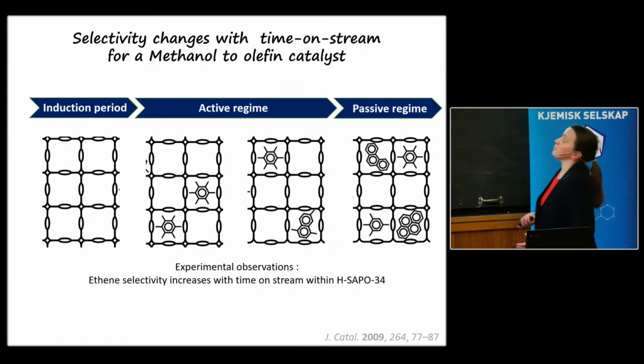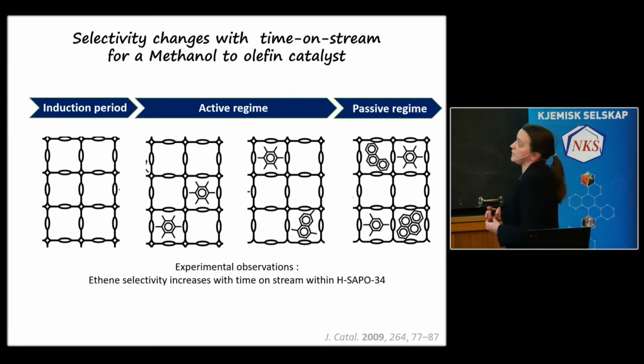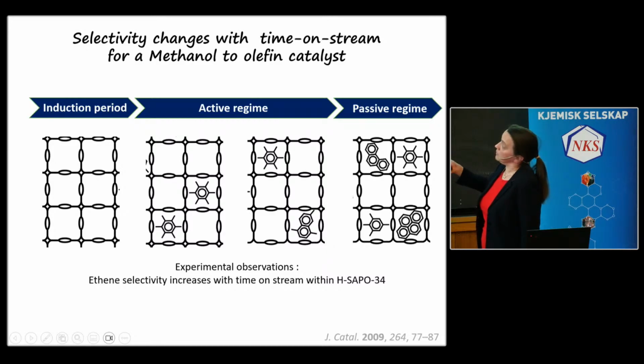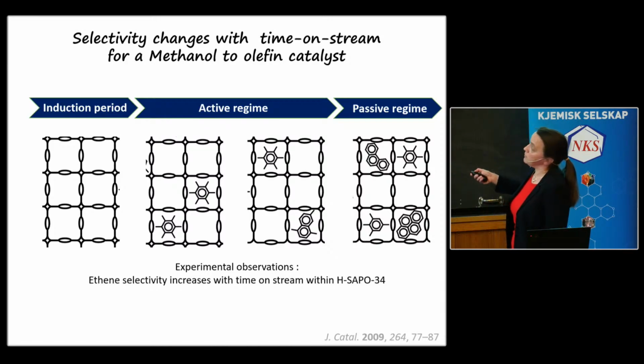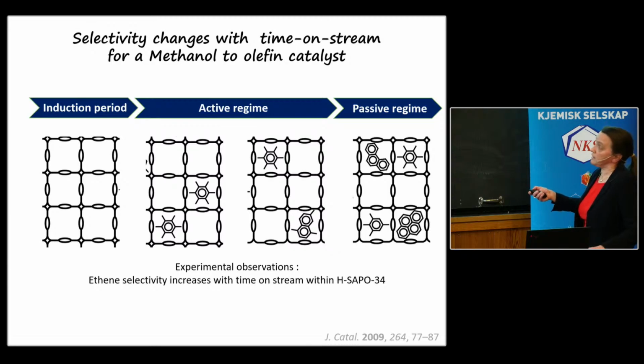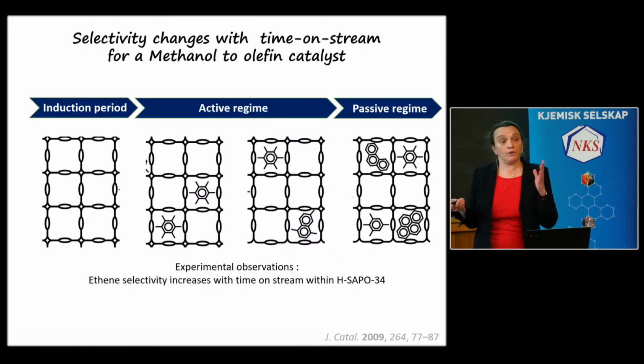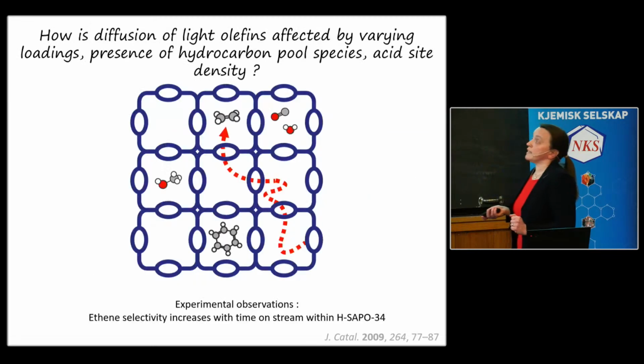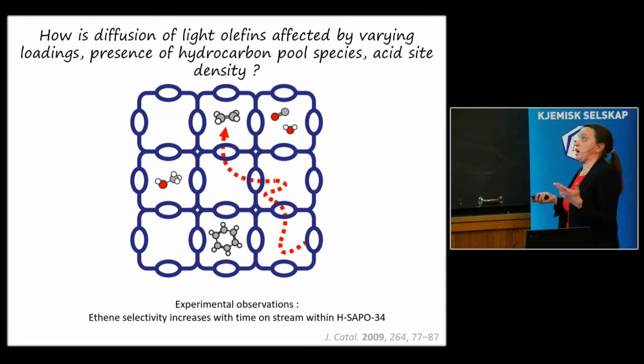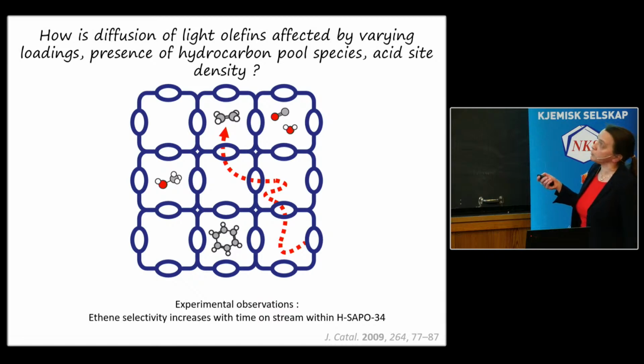Yeah. What they also saw with time on stream is that in a catalyst, it was a catalyst with cages. It was SAPO 34 catalyst with cages and small windows. They saw that with time on stream, the selectivity for ethene increased. And so the question is, is this due to the cause of reactivity, or is this due to the cause of transport? Yeah? And so that is the reason why we then started to try to understand, can we understand this transport of these molecules through this zeolite system, let's say.